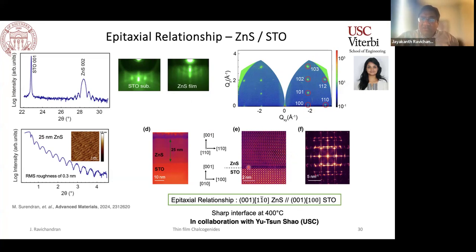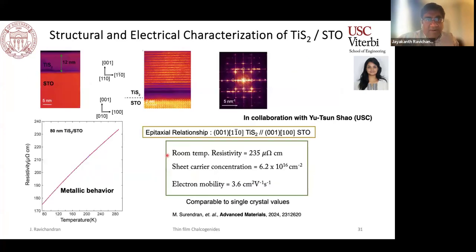And when you combine with STEM imaging and looking at the in-plane relationship, we were able to map out the exact in-plane relationship in these cases. So even though you're trying to grow a tetrahedrally coordinated chalcogenide on STO, it turns out you can get fairly good epitaxial relationship and reasonably high quality materials in this case when you're trying to grow these binary materials.